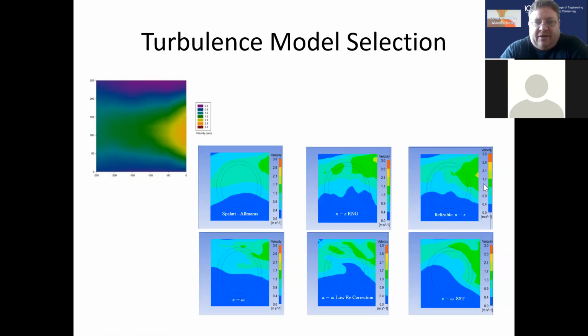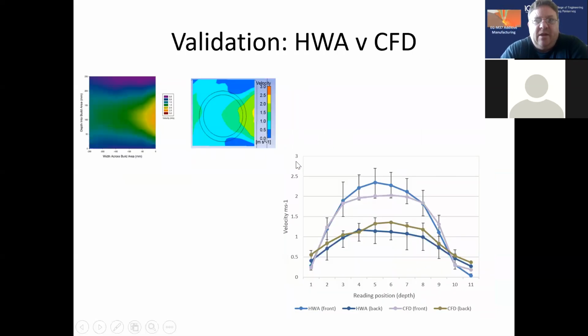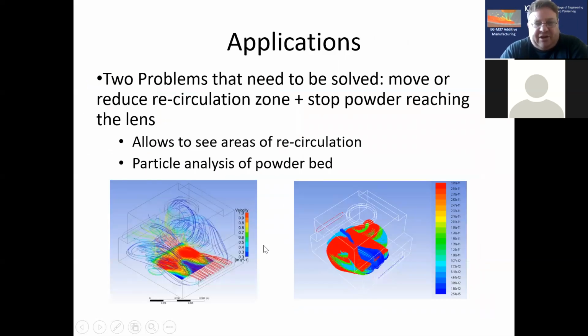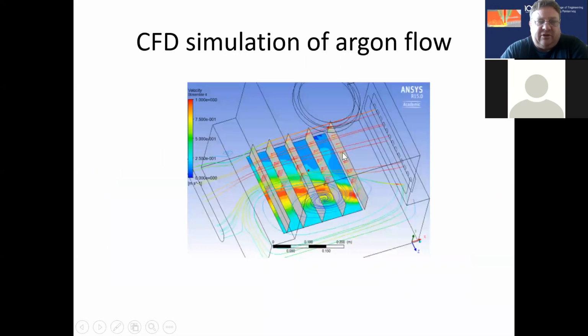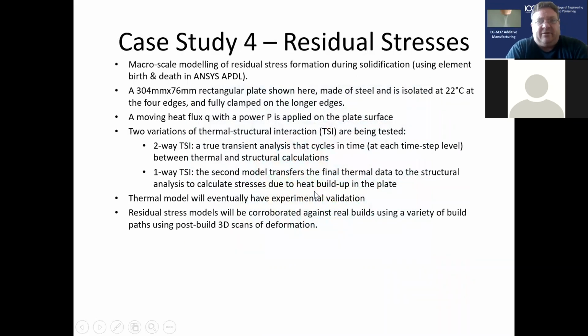And you can see here that they don't all match perfectly, but through changing the model parameters, we were able to fine-tune to the point where you can see a relatively good correlation between this turbulence model here and the hot wire anemometry on the left-hand side. And it shows you how you get hot spots on the bed. You can see here very clearly a recirculation on the bed, and this is going to lead to differences in porosity, and we know that that does happen, and we have been able to correlate it with the gas. Just another example of how CFD is used.